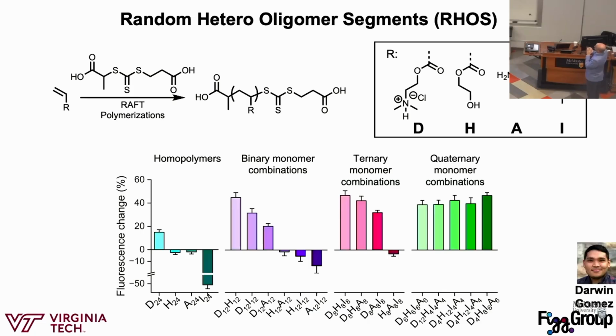You may say these look the same. These actually have different dissociation constants. So we can change the fluorescence and make green fluorescent protein more fluorescent than we can express it to be. And we can change the dissociation constant according to the composition of the oligomer, which is really interesting. But what we're really excited about is that we really do need this combination of 3 or 4 different monomers to get these high increases in fluorescence of the GFP.